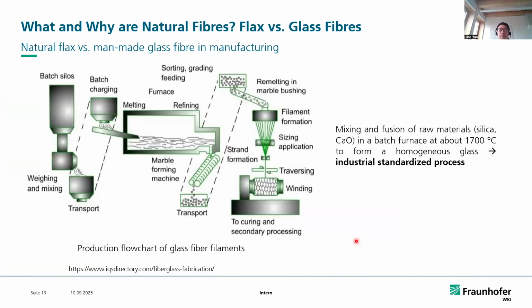Let's take a look at the manufacturing of the glass fibers. I would say the production of glass fiber or glass fiber yarns is an industry-standardized process. The raw materials like silicon and calcium oxide are mixed and melted in the furnace at a temperature of about 1,700 degrees Celsius to form a homogeneous glass. After that, it is refined and drawn into glass filaments with very constant structures.